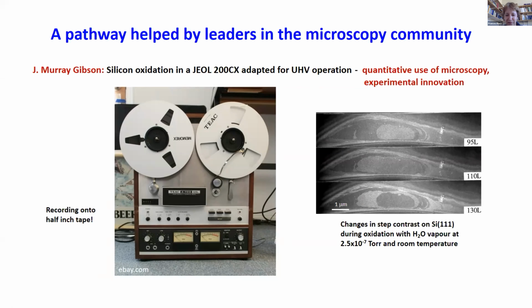We wanted to do silicon oxidation. We oxidized silicon in a microscope adapted for UHV operation so that you could clean the silicon surface, have it really clean, and then introduce controlled amounts of oxygen or water vapor at a particular temperature and record the results. So these images use the forbidden reflection mode, which is one of the diffraction spots that does not exist for an integral number of unit cells, but it does if you have a fraction. So you can follow steps on the surface as you oxidize. And we recorded onto this reel-to-reel tape, and it was expensive. So we had 60 minutes. And then when it was over, we had to find another tape, and then we had to delete the first one once we'd copied it over.